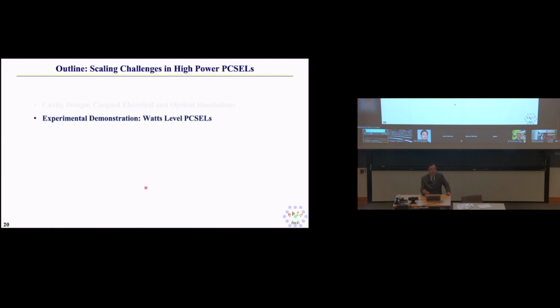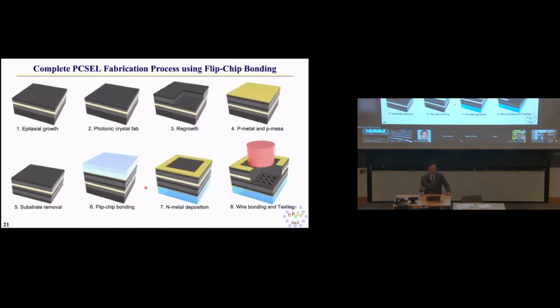So now let's look into, can we demonstrate this? What performance can we see here? There are also lots of challenges, as you can see. Here is just the fabrication process flow. Generally speaking, we start with so-called epitaxial growth. That means a wafer, let's say a gallium arsenide substrate. Then we grow the heterostructure based on our design, different kinds of layers for laser formation.